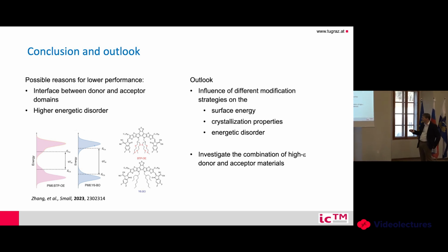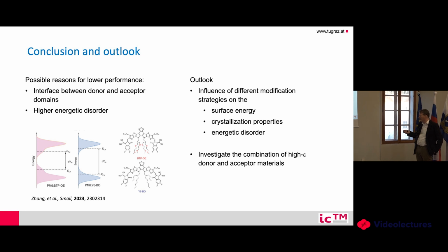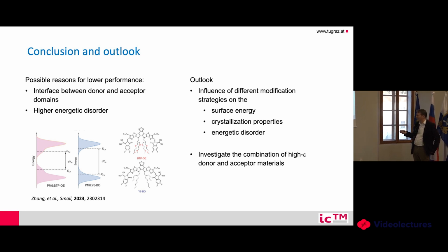And at the same time, I think one month before or after us, a Chinese group, together with a German group, published a paper with a very similar material synthesized. They also have these ethylene glycol side chains, different ones, but the same idea, and they also found out they didn't get better solar cells with it. They went a little bit more into electronic investigation and found that they have a higher electronic disorder, which destroys the good electronic properties. So this is also research. You have a good idea, which in principle should work, but then in the details, it's not as good.